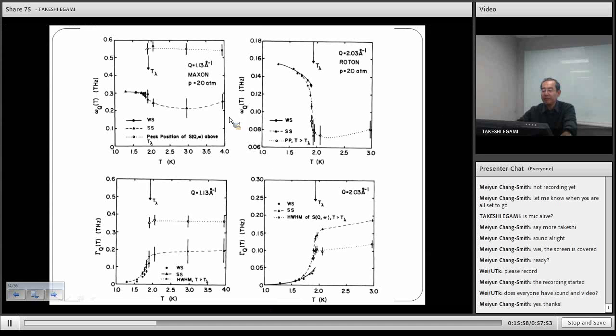So if you plot frequency of this particular mode, this is a roton mode. Frequency increases when the system goes into superfluid, but at the same time the width becomes very, very sharp, right? Because the system is a superfluid, so atoms do not interact with each other. It's in a condensed boson state. So this phonon scattering becomes less and less. Yeah, the one that we discussed last time. The dissipation due to this phonon-phonon interaction becomes much less. So this is very much like phonon becoming sharp in the superconducting state because of the absence of electron-phonon coupling within the gap.